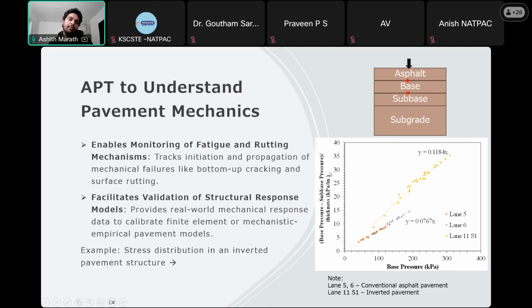The idea is that you can think of the y-axis as representative of the modulus of the base layer. If you assume a linear, conical distribution of the stress along the depth, this can be considered representative of the modulus of the base layer, and the x-axis is the vertical pressure at the top of the base layer. As you can see clearly, there is a stress dependency of the modulus of the base layer. And when you compare the conventional pavement, lanes 5 and 6, to lane 11, the inverted pavement, you can see a clear difference in the trend.